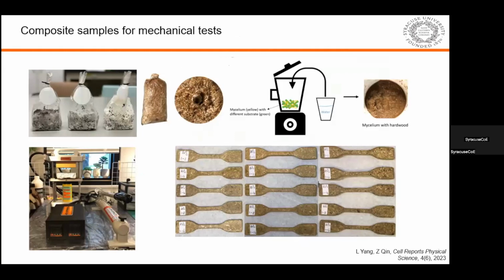So based on that, we move forward to the lab. We grow mycelium together with wood fibers, and then we culture the mycelium. After culturing, we turn that into dog bone samples, and then we use a heat press to control the temperature and the pressure to press that into a dog bone sample.